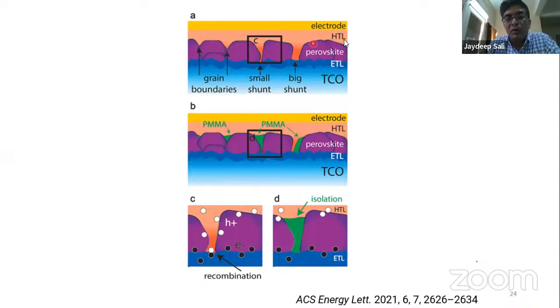So when you deposit a hole transport layer over the perovskite, as can be clearly seen here, there is a shunt between the hole transport layer and electron transport layer. It is a big shunt here, a small shunt here. Okay, and therefore if you add some organic additive into it, as shown here by this green color, then you can fill up these grain boundaries, and you can prevent formation of these shunts, which can definitely improve the structure or the stability of the perovskite films.